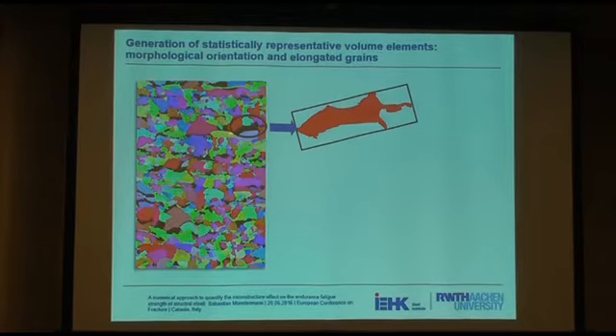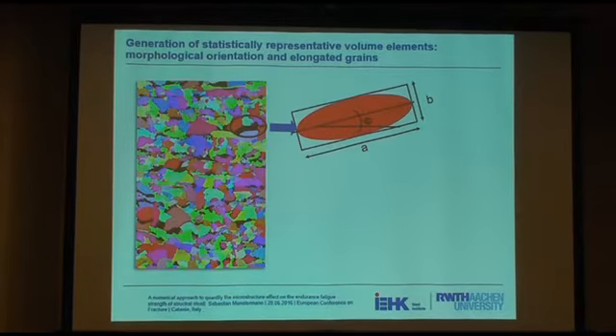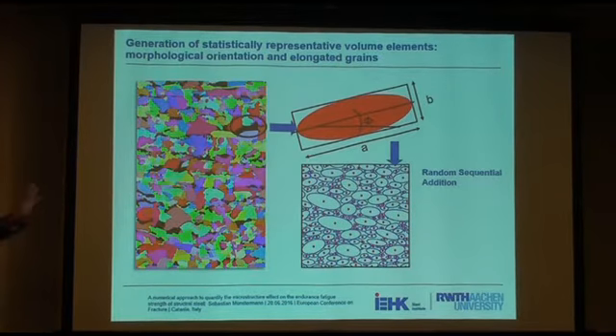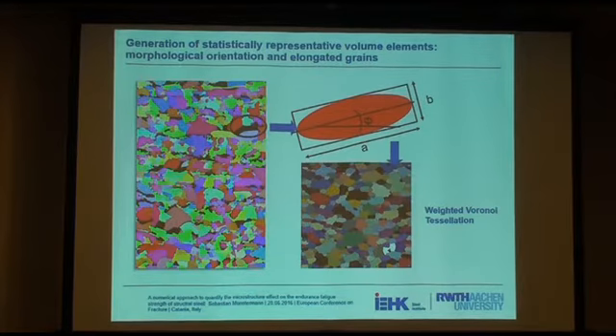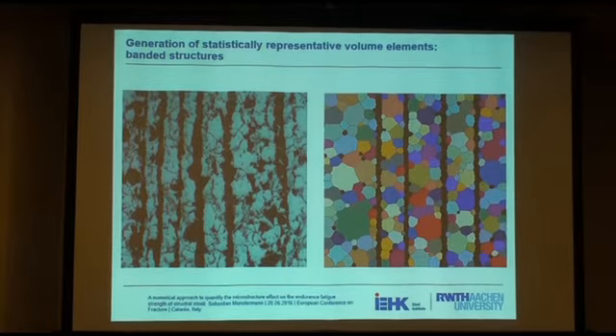Of course, what's also important are some morphological parameters of the microstructure, for example, the elongation of grains and the morphological orientation with respect to the rolling direction. This can be measured by the same approach, and then you can run the so-called random sequential addition algorithm. This is an algorithm that puts the seeds for the later grains into the predefined box. There are some rules: you have to reserve a certain space where no other seeds may be placed. Once you have put your seeds into the box, they should not be moved anymore, and there may be no intersections of these boundaries that we've reserved for the grains. Then you run the multiplicatively weighted Voronoi tessellation algorithm and you create such a microstructure model.